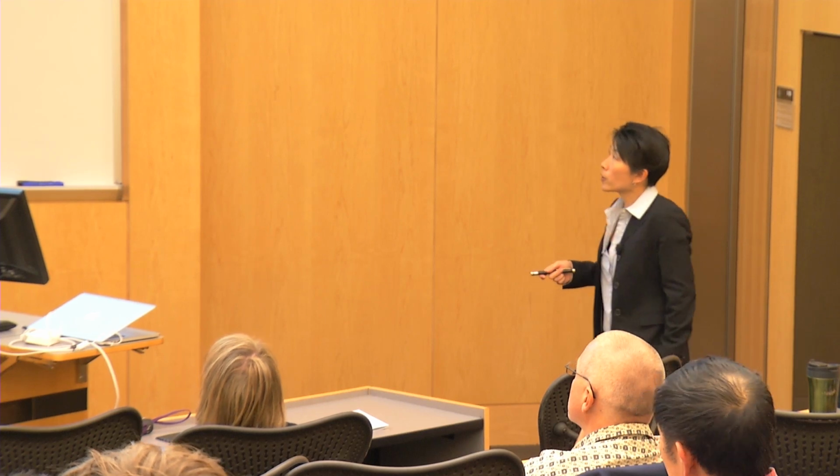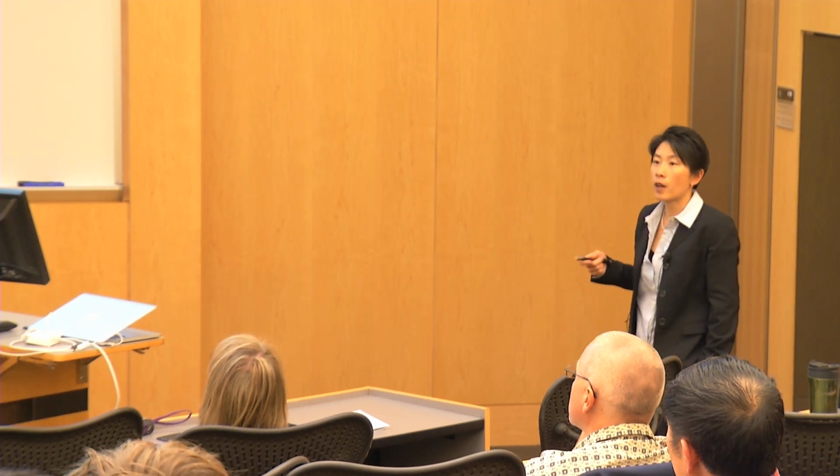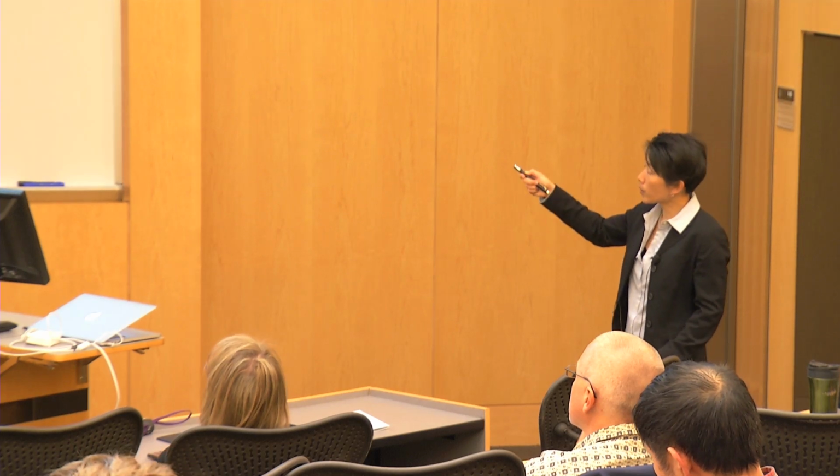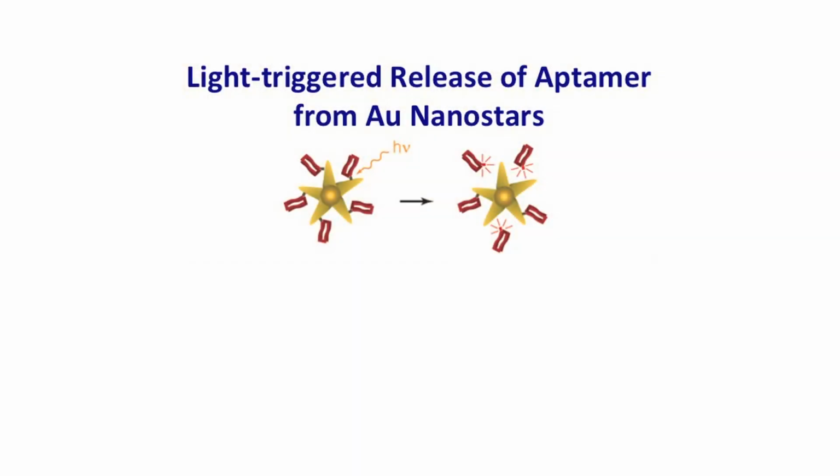Okay, but then what we were interested in is, are there any adverse effects if we tried to release the drug? So in this case, the drug is trapped on the nanoparticle surface. And so what we did is we ended up shining near infrared light, but we only want to shine light for 2 seconds, okay? We'd rather not shine light for 5 minutes, which is a long time. But if we shine light for 2 seconds and we use femtosecond pulses, we can actually break chemical bonds.